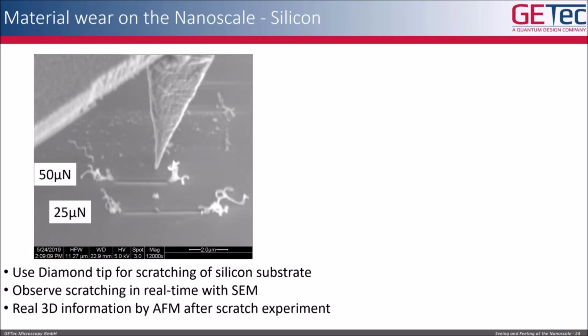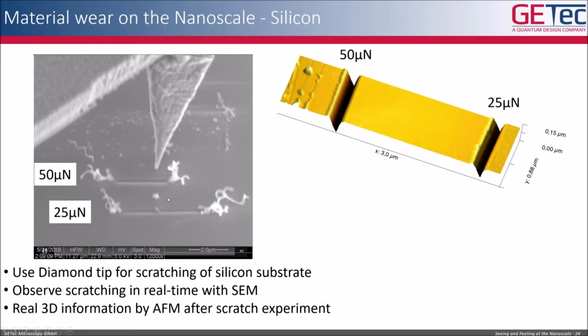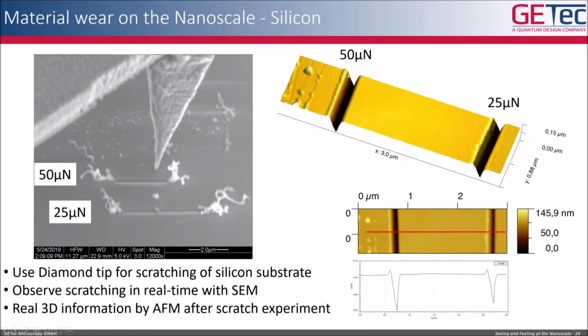We did this experiment with two different force loads: in the lower part with 25 micronewtons, in the upper part with 50 micronewtons. You can then use the same tip after scratching to make a high resolution AFM scan of these scratches, here for the 50 micronewtons and here for the 25 micronewtons, and get a very good characterization of the scratch geometry created with these diamond tips.